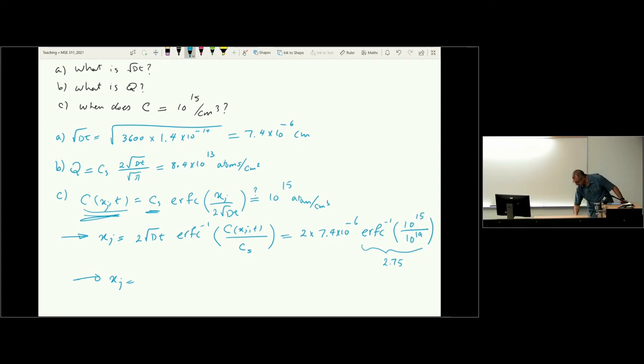let me see, 4.1 times 10 to the minus 5 centimeters, or if you want to convert it to micrometers, it's 0.41 micrometers, or 410 nanometers. So it happens about half a micron below the surface. You can see that going from 10 to the 19 to 10 to the 15 is just 0.4 microns. Okay, so moving on, let's look at another possibility.